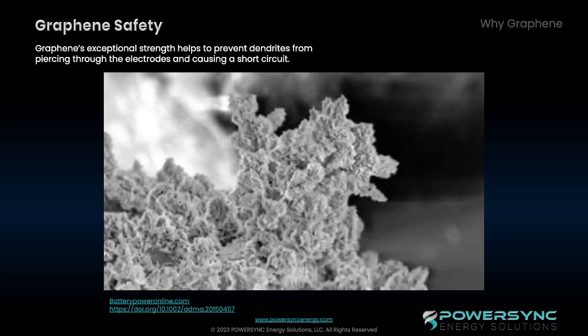In addition to that, the strength of the graphene means that it can help to improve the safety of the lithium batteries by preventing the formation of dangerous dendrites. A lithium ion battery operating under abnormal conditions, such as overcharging or low temperature charging, can lead to a harmful phenomenon called lithium dendrite growth or lithium plating. Lithium dendrites are metallic microstructures that form on the negative electrode during the charging process. They form when extra lithium ions accumulate on the anode surface and cannot be absorbed in time, causing short circuits that lead to catastrophic failures and even fires. Graphene's exceptional strength prevents dendrites from piercing through the electrodes and causing that short circuit.